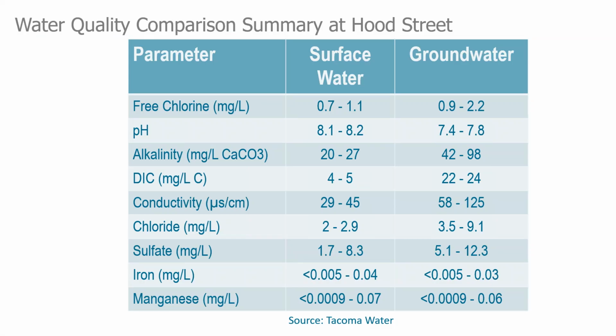Here's a look at the chemistry, the general conditions that occurred during the testing at Hood Street. A couple things to point out is that the pH difference that we talked about between 8.1 and 7.4 to 7.8 were the 2 treatment endpoints. The chlorine was pretty high at this location, and that's going to, of course, impact our results, and I'll talk about that. But I also want to point out the difference in the alkalinity and the dissolved inorganic carbon, the DIC. Quite a difference. This is very typical of the Pacific Northwest waters, where we have soft, poorly buffered, low mineral surface waters coming from those watersheds, and then more mineralized groundwaters.